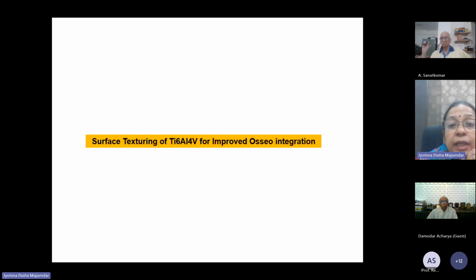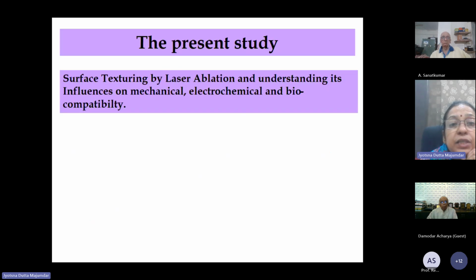So now we also try to improve the osseointegration property by surface texturing. Usually, as I mentioned, people do apply sand blasting, but whenever you apply sand blasting, there is a random roughness on the surface, and that random roughness causes cell growth in a random fashion. So we tried to observe the effect of periodic structuring or periodic roughening on the surface, and its effect on cell attachment. So we use a laser ablation technique.